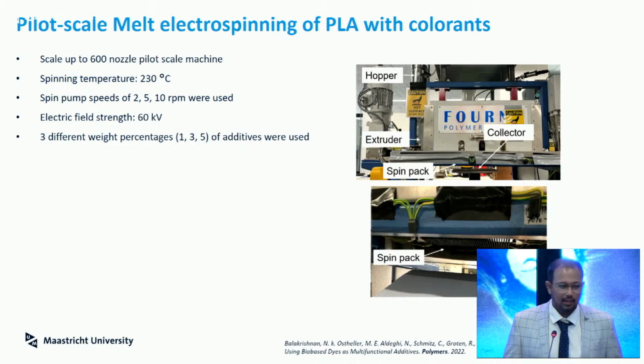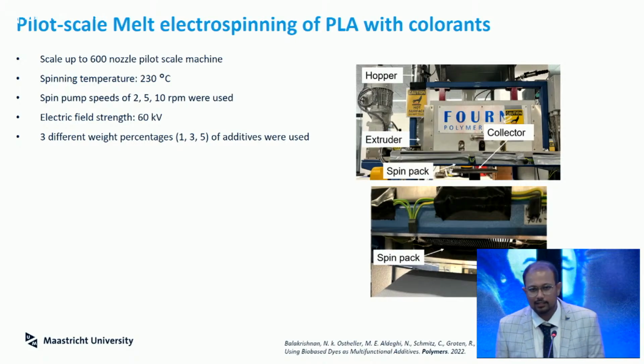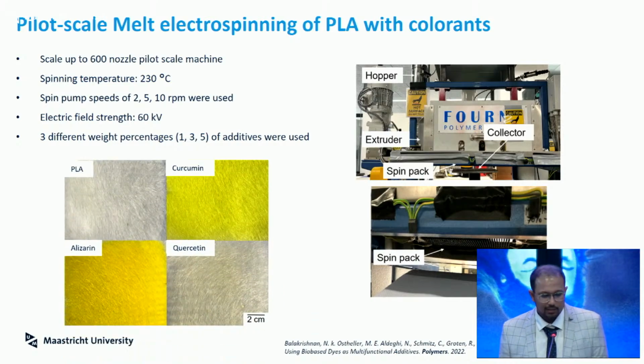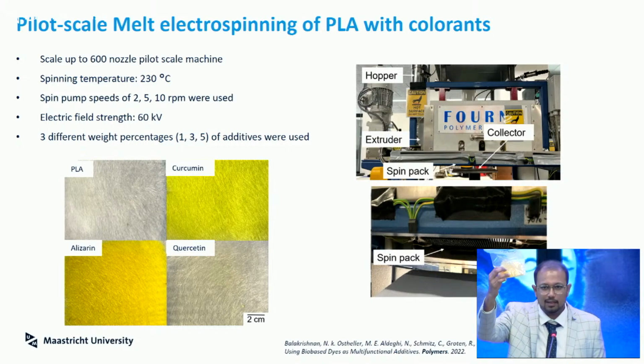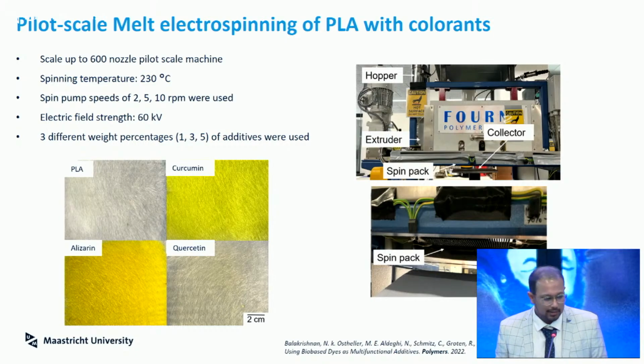That was quite promising. In the end, I started from lab scale, where I was working with 2 to 3 grams of material, and went into a larger scale where I was working with, let's say, 0.5 kilo to 1 kilo of polymer. So it's still not industrial scale, but the process is still in its niche market, and it's still upcoming. During this, I did the electrospinning trials, and as you can see in the picture, these were some of the samples I made, especially with the colorants alizarin, quercetin, and curcumin, because from the list of colorants I was working with, these three, according to literature, had some antibacterial activity.